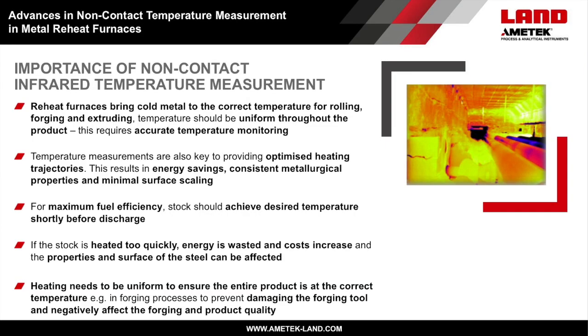So, what's the importance of continuous thermal imaging temperature measurement of the entire metal stock? Reheat furnaces bring cold metals to the correct temperature for rolling, forging, and extruding. The temperature should be very uniform throughout the product, which requires accurate temperature monitoring and controlling. Temperature measurements are also key to provide optimized heating curves. This results in energy savings, consistent metallurgical properties, and minimal surface scaling.